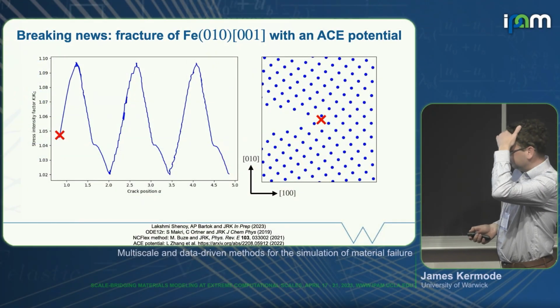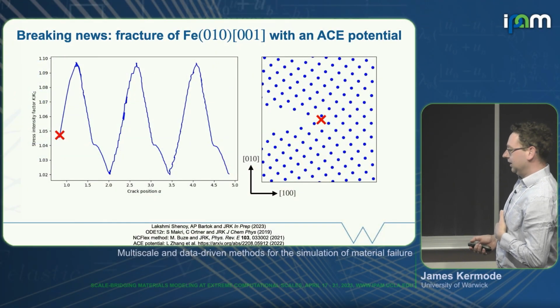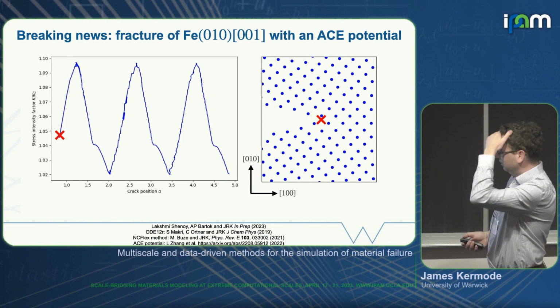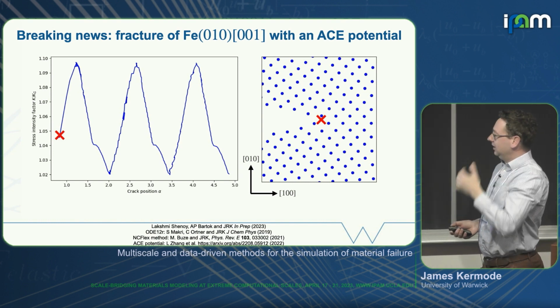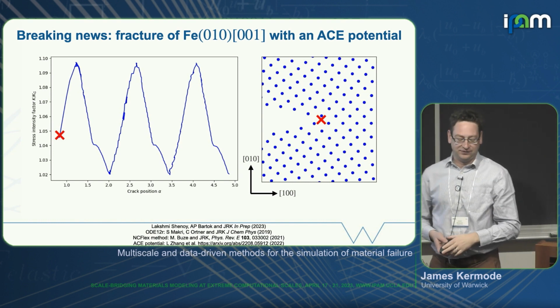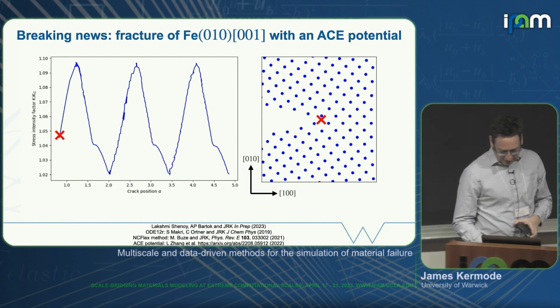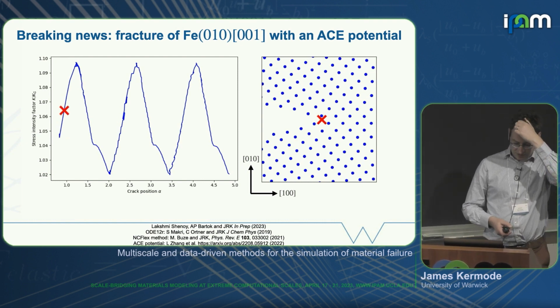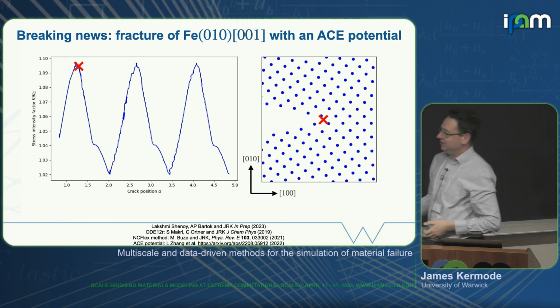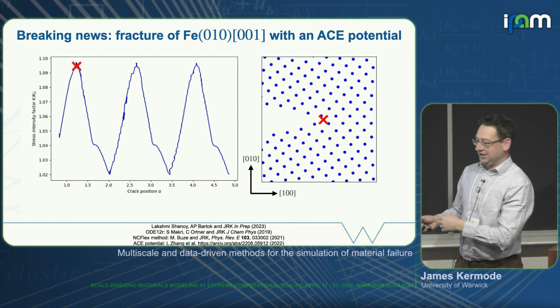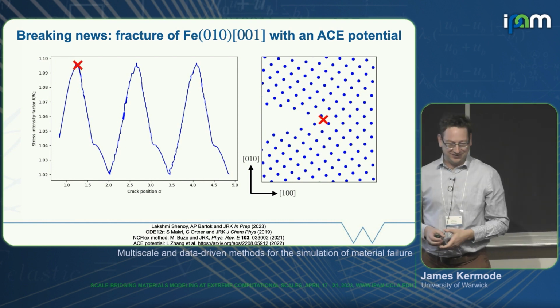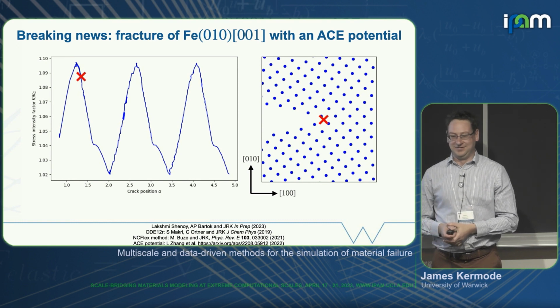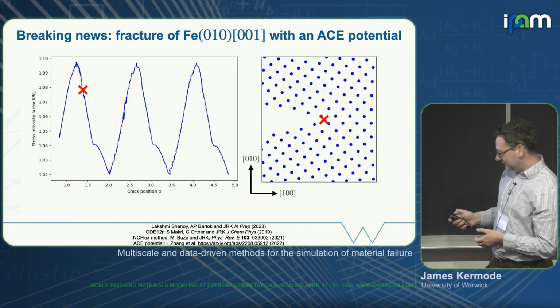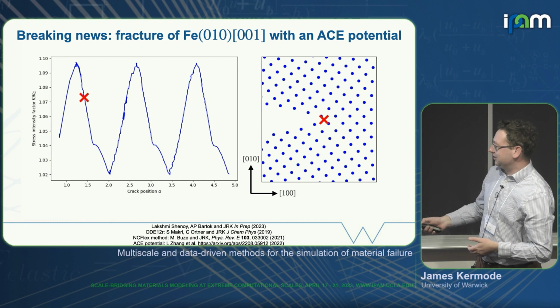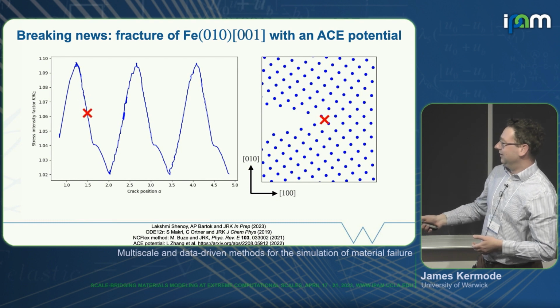This is a potential fit by Lei Zhang, involving Gabor and Francesco Maresca from Groningen, using the ACE scheme that we heard about from Christoph in the previous talk. And we've managed to get it working with this numerical continuation scheme. You can see I'm taking rather big steps here, so it's not as nice and smooth as the previous result, because the potential is much more expensive. That's something that we can further refine. But the good news is that it basically works. We get the solution path coming out very nicely.